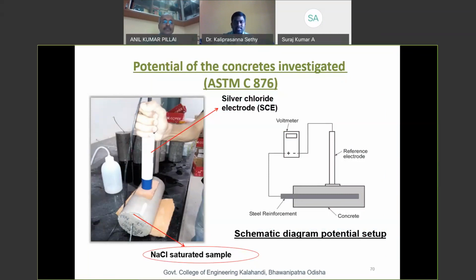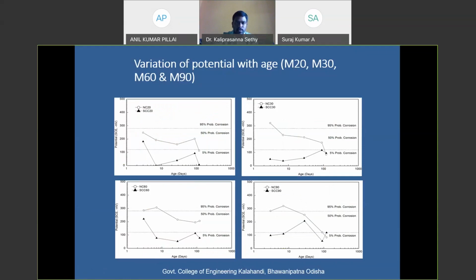Sure, sir. So here is the potential test of the developed concretes. This is the indirect way to check the probability of corrosion. For that we have taken a silver chloride electrode to check the potential of our developed concrete. From the schematic diagram you can see the samples designed for this test. Inside the 10 by 20 centimeter cylindrical sample, we have provided an 8 mm reinforcement bar exactly at the middle of the cylinder, and the bar is connected with a low resistance copper wire to the positive side of the voltmeter, and the negative terminal is connected to the silver chloride electrode. By using this method we calculated the potential values for our concrete.